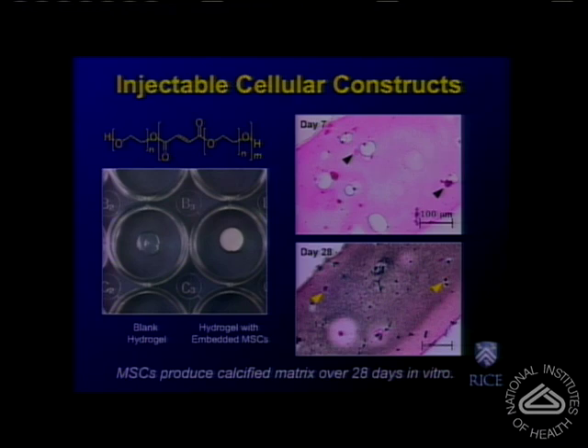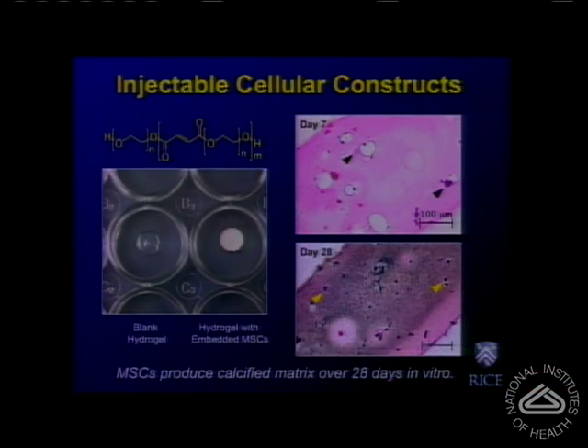It's an unsaturated polyester. It's an alternating copolymer of fumaric acid and polyethylene glycol. Because of the unsaturated double bond along the macromolecular chain, the material can cross-link and polymerize. And here we have an example of the polymerization of such a material in the presence of mesenchymal stem cells, and the culture of these constructs of hydrogels with encapsulated cells for a period of 28 days. So what one sees is that the cells not only survive the encapsulation process, the chemical reaction at 37 degrees Celsius, but as the cells mineralize, the cells differentiate and produce extracellular matrix that is mineralized, as shown here in this histological section that is stained with Von Kossa staining.